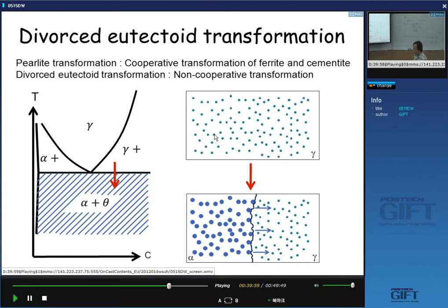That is the way not to make the cementite in lamellar structures. And that's why we need those kind of seed, cementite seed, to make this round shape cementite. So now you can understand why we need very slow cooling rate over here. When we apply fast cooling rate, there is no time for carbon to diffuse onto the cementite particle around the interface. So it just precipitates as a lamellar cementite.